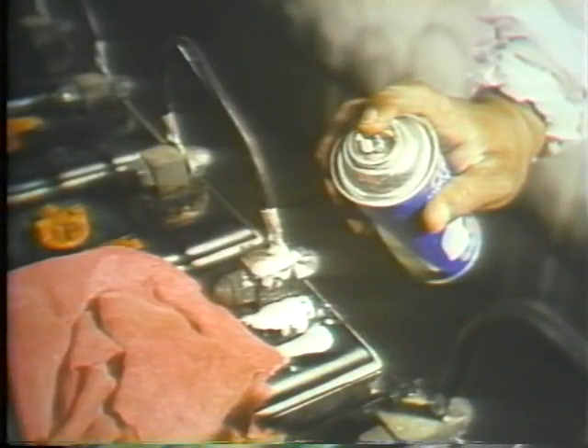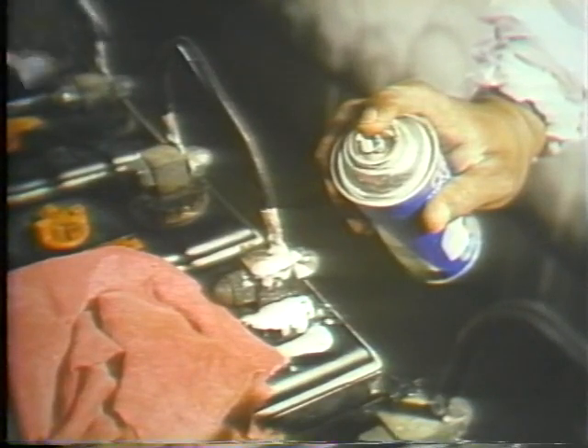With the vent still covered, use battery cleaner or a baking soda solution or ammonia to neutralize any acid on the terminal. After the solution has stopped foaming, wipe it off with a rag. To prevent more corrosion in the future, coat with either a special spray coating or grease.